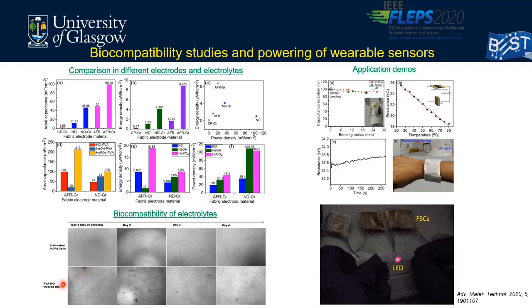Then we carried out the same experiment for the PVA-KCl medium also. In the PVA-KCl medium, we can see that with an increasing number of days, the HDFC cell, that is the human dermal fibroblast cell, shows cell growth. This concludes that the formulated PVA-KCl gel electrolyte is a biocompatible electrolyte. It doesn't show any cytotoxicity with the human dermal fibroblast cell, so it can be safely used for wearable application.